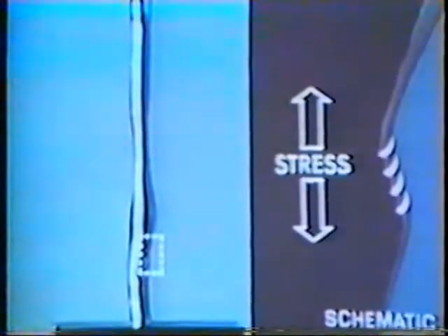The offsets produced on the surface when adjacent regions slide past each other appear as lines and are called slip lines. Actually, as can be seen by magnifying a portion of the surface, slip usually occurs on a number of planes in a narrow region. These slip bands are closely packed groups of slip lines. The offsets at the surface are about 2,000 angstroms, while the distance between slip lines is about 200 angstroms.